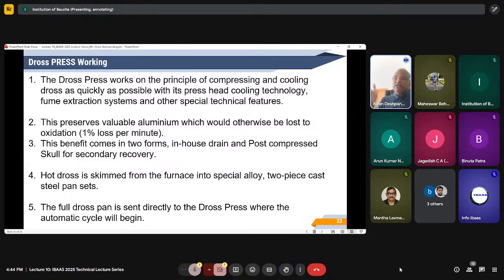So what we do is we provide the DROSS pans which are of special alloy, and it is a two-piece cast steel pan set. So the pan set is top and bottom. When the DROSS is taken into the top pan, the entire assembly goes into the press, and when it is pressed, the liquid aluminum drains into the bottom pan. You get ready-made ingots, which is an alloy which you can directly put into the furnace. The full DROSS pan is sent directly to the DROSS press, where the automatic cycle will begin. Why is it automatic? Because once the DROSS pan is put inside, just press one button and everything will be automatic.